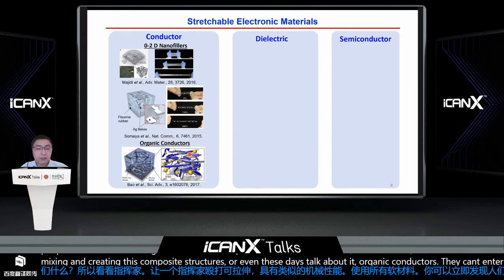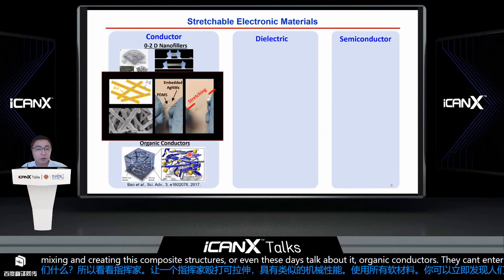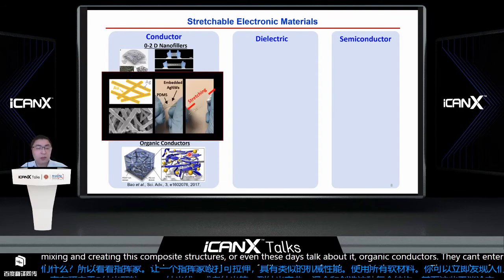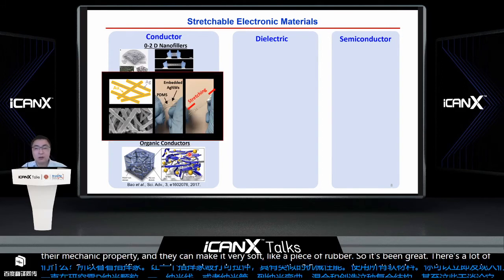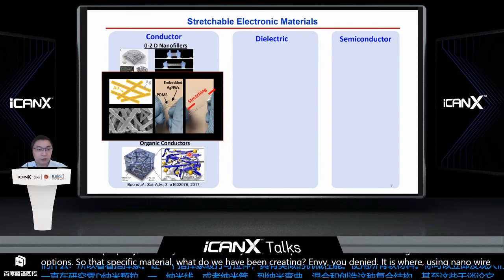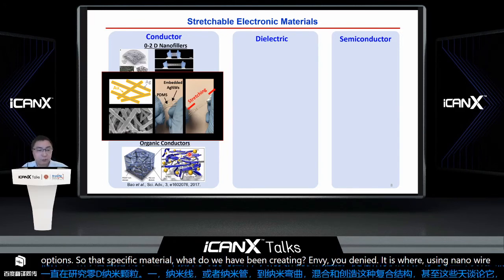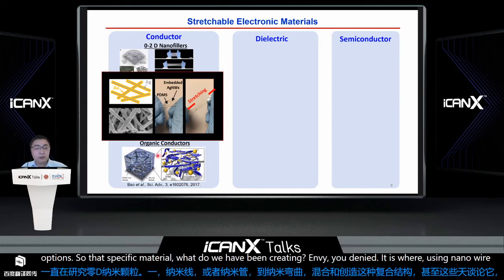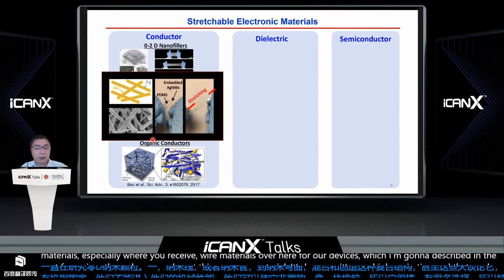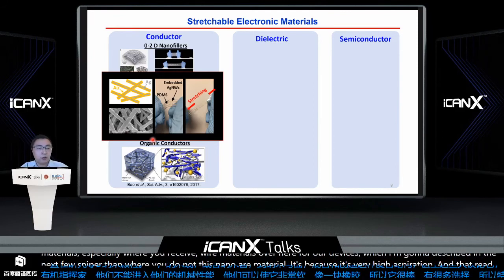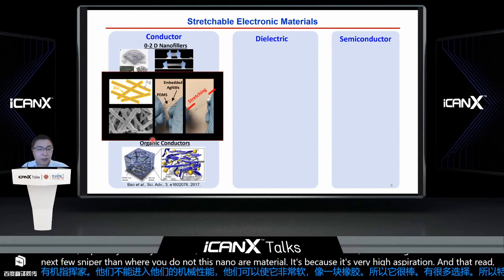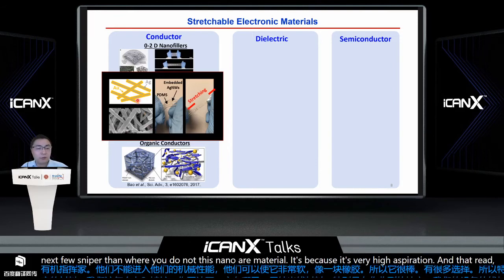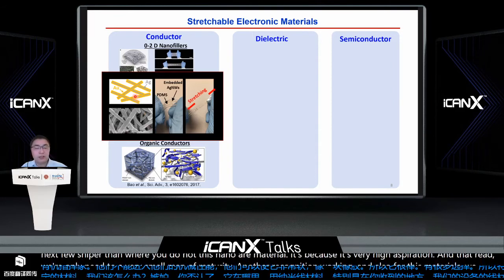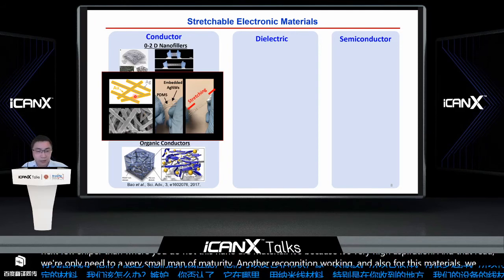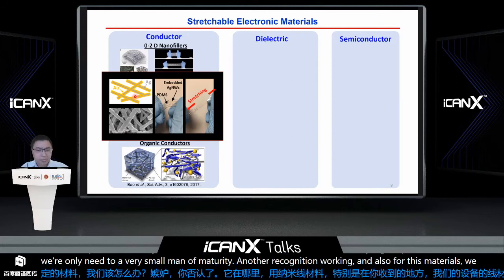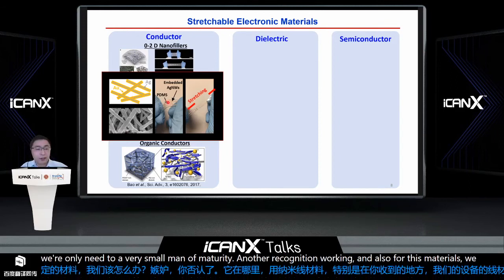The specific material we have been creating and utilizing is nanowire material, especially silver nanowires for our devices, which I'm going to describe in the next few slides. The reason we utilize this nanowire material is its very high aspect ratio, so we only need a very small amount of material to allow percolation. Also, we care about the surface functions that we can chemically modify to allow a match between the semiconductor and the conductors, creating ohmic contacts instead of Schottky barriers. So basically, the message is that there are tons of options for conductors.